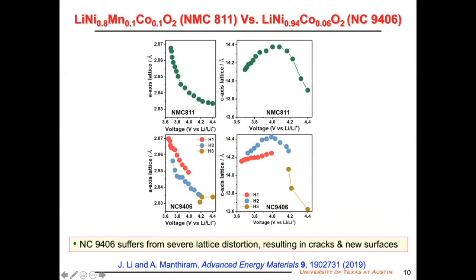Of course, we keep the cutoff voltage 4.3. As you increase the nickel content, the voltage slightly decreases. So with the same cutoff voltage, you can get higher capacity with a higher nickel content compared to a lower nickel content. That means when you charge it, you get lattice parameter changes in the C parameter. So that creates cracks. When you create cracks, you also create new surfaces. So the interaction of the cathode surface with the electrolyte keeps continuously increasing as we cycle.